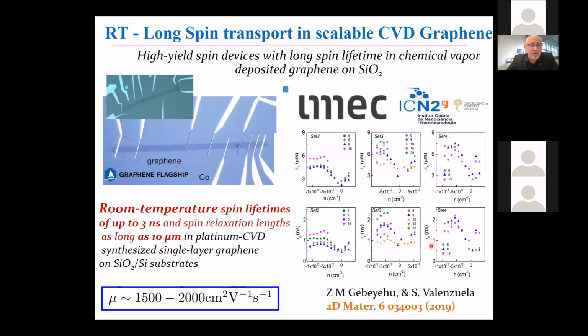In parallel, there were efforts in the consortium to systematically study spin transport in polycrystalline graphene. And in this work by IMEC and ICN2, there was an analysis of many devices, and at the end, they were able to characterize the upper limit, which turns out to correspond to the simulation, in the order of 10 micron at room temperature, even though you see that the mobility of this graphene is not as good as the very high quality exfoliated graphene sample. But anyhow, this value of spin diffusion length is really very good for moving forward into our objectives.